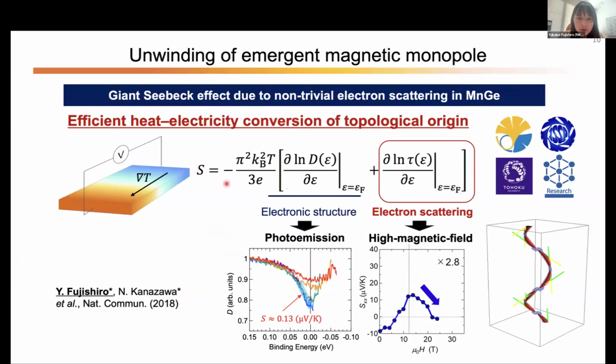So it is known that the Seebeck coefficient has two contributions. One is from the electronic structure, and the other is from the electron scattering. So we actually did a photoemission study to directly evaluate this first term, where we find a very negligibly small Seebeck coefficient.